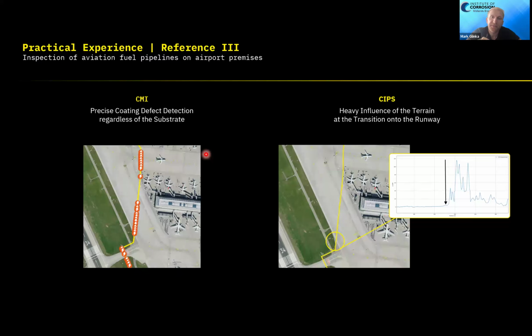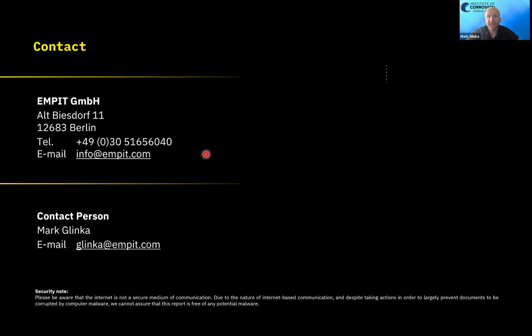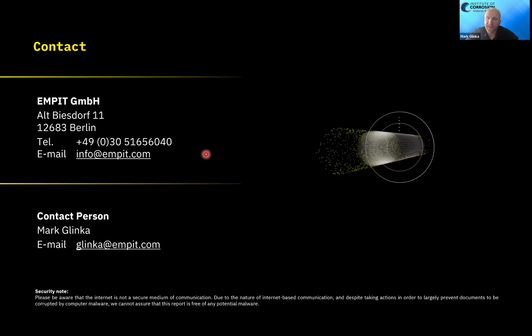And I want to finish with the biggest limitation that CMI has at the moment. We can talk about corrosivity. We can tell you it's active, and we can obviously also tell you it's passive. We get better and better with corrosion growth rates, so we can also tell you how many micrometers per year you will be losing. But we cannot tell you the absolute wall loss. We are not a flying pig. It's not possible for us to tell you, hey, here you have 25% metal loss, here you have 18% metal loss.